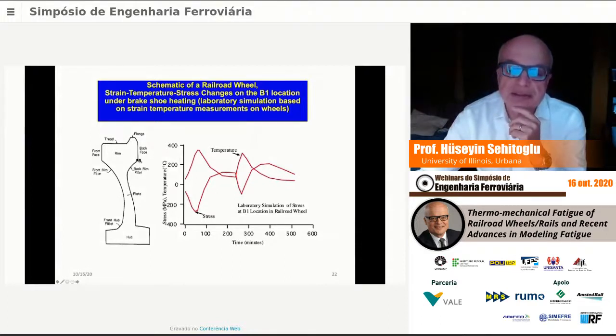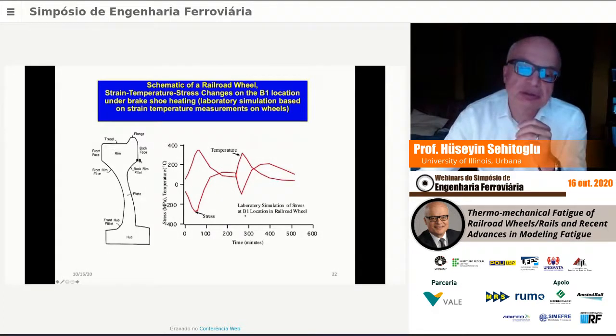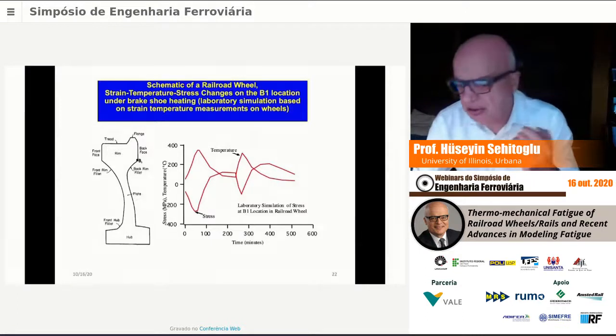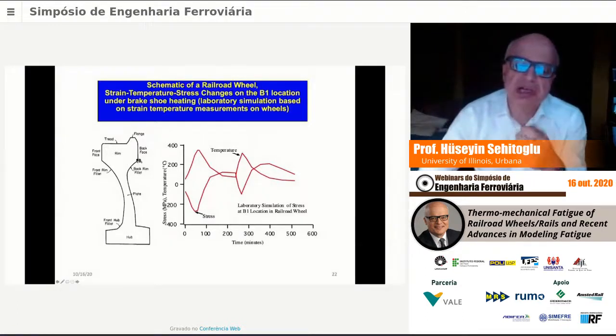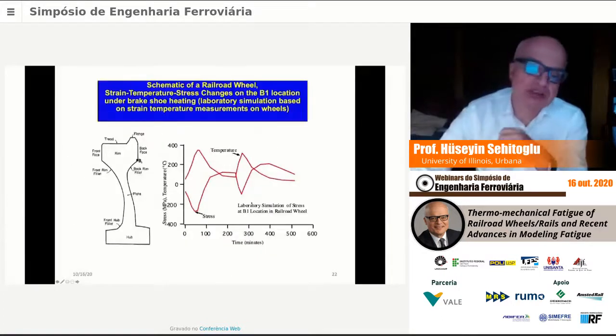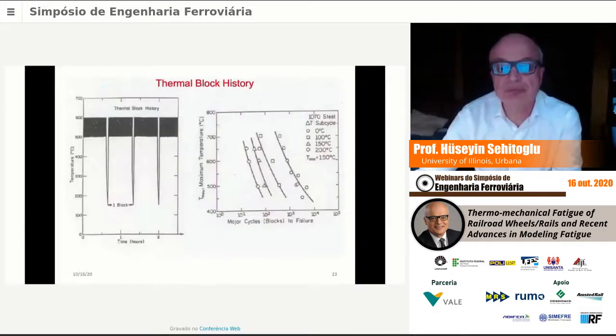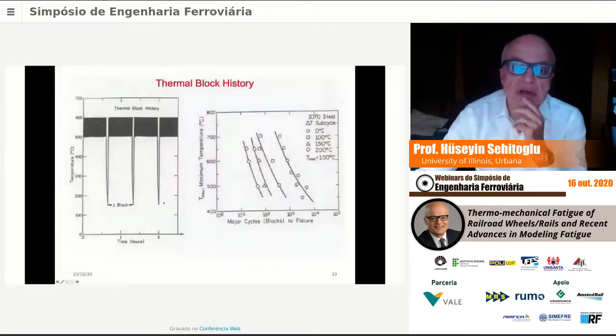You could see that for this material, even in the B1 location, of course, the stresses are not that high. This stress is 200 MPa, but there is a buildup of stress. So this is the temperature cycle, and this is the stress. This is actually not a finite element analysis or anything. This is just applying temperature and strain on a small laboratory sample and looking at the effect of that. Now, other things can be done, of course.